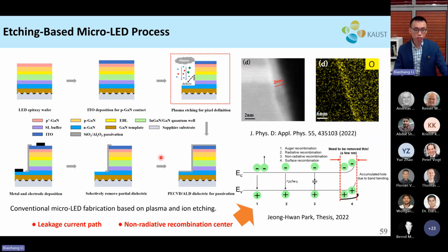The sidewall damage during the plasma etching process. So the plasma etching process is the dominant process used to fabricate most of the LEDs, including micro LEDs. In this process, you have to have accelerated particles from the plasma to etch and form the pixels, right? So in this process, you can introduce a lot of leakage paths and non-radiative recombination centers.